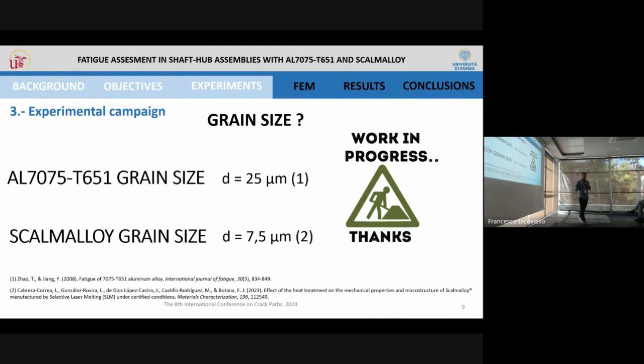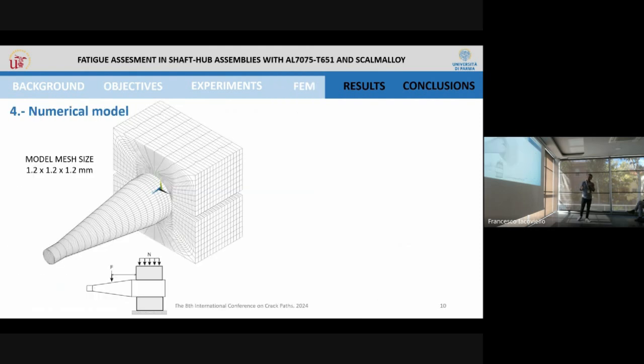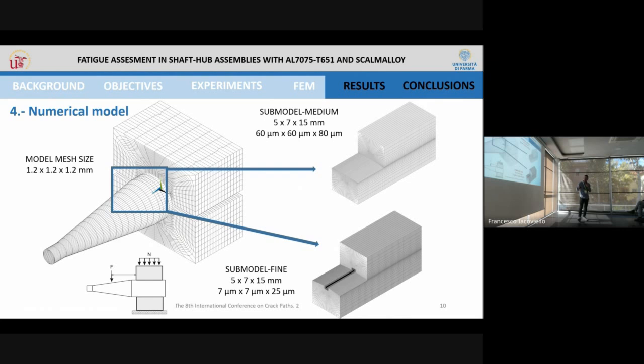So up to here, we have defined all the experimental part. Now we move to the numerical part. We have designed this model to reproduce the complete test. We have done one model with a coarse mesh size of 1.2 millimeters, and then we have used the submodeling technique focused on the stress concentrations to be more accurate in the critical zone and decrease the computational time.